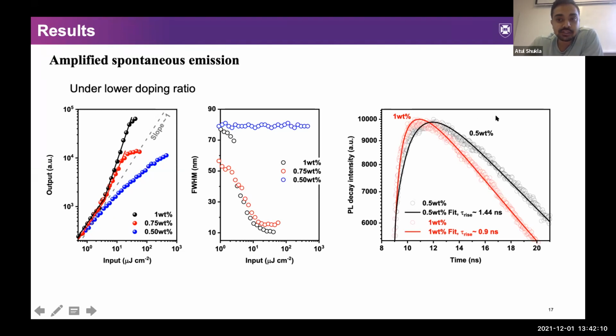As a result of this, longer rise times mean poor energy transfer. And due to this, the lifetime of the DPP is dominated more by the TADF material. We have a lifetime of close to 17 nanoseconds in the case of 0.5 wt%, while in 1 weight%, we had a lifetime of 9 nanoseconds, which is close to the intrinsic lifetime of DPP. So this, again, helps us understand why there is increased bimolecular quenching in the case of lower doping ratios.